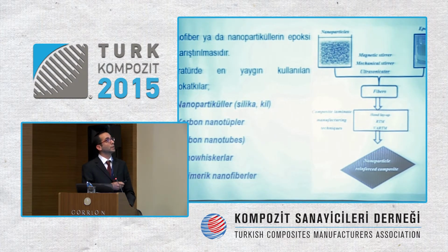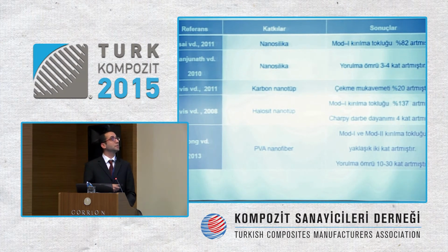And about the materials, nano additives are used. Ultrasonic devices are used and they're mixed into the resin before the fiber composite material is created to manufacture. Nanoparticles are the most commonly used, like carbon nanotubes or spherical systems. Here we see certain studies in the literature, different contributions by different scientists. Here, for example, nanosilica usage indicates that the fracture toughness mode has increased with nanosilica.